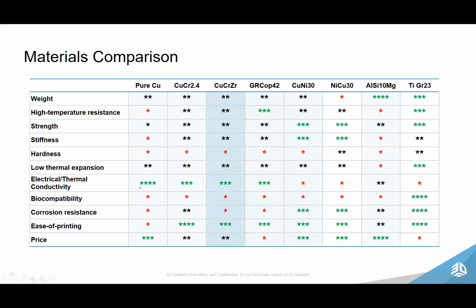Now, pure copper obviously is going to have excellent thermal conductivity and electrical conductivity. It's not going to be as hard or as stiff as other materials. It's going to be quite soft. But there are definitely different alloys which give you advantages if you go left to right over pure copper as you add elements. Copper nickel 30 is quite interesting to us because it is a nickel copper alloy, giving a good combination of copper properties, but also the nickel corrosion resistance, which is typically going to be the primary need for saltwater resistance.